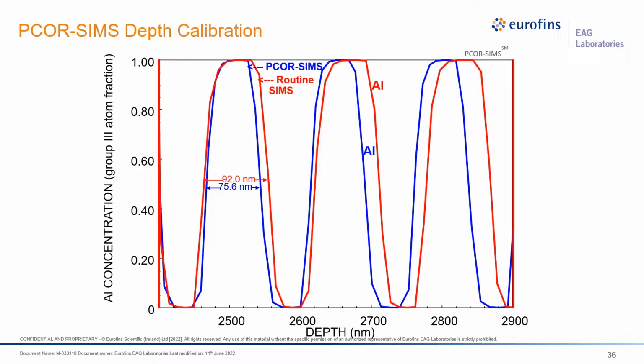Obviously, another prerequisite for the successful growth of a VCSEL is to accurately control the thickness of the many layers that make up a working device. Nowhere is this more important than in the DBR, where the thicknesses must be correct to tailor the optical properties of the mirrors. Determining the correct layer thickness with conventional SIMS is not easy because changes in alloy composition alter the sputtering rate. If no corrections are made, that's the red curve, the plotted layer thicknesses can be in error by approximately 20% with respect to the PCOR corrected profiles, which are in blue.